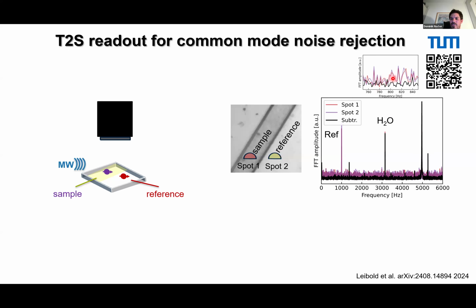And we see here that nicely the noise is very correlated, and this is exactly the point: if you are limited by microwave noise, of course, you would encode this on both positions. And you can easily subtract this, and then you can reduce the noise, depending, of course, on the quality of your microwaves. We saw here a factor of 2 to 3 improvement, even with a pretty good signal generator. Of course, if you have different systems, this may have a much larger impact for noise cancellation. And of course, the nice thing here is if you also correct for laser noise, you can remove most noise sources with this approach. And again, in a very simple way, you only have to upgrade your AOM with 2 frequencies. So the first application is noise cancellation.